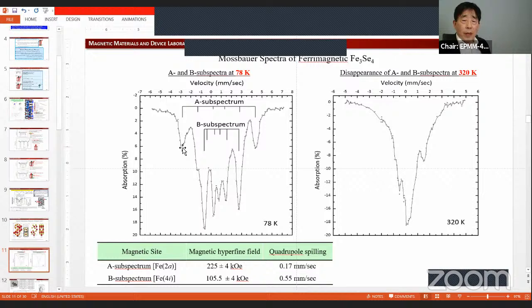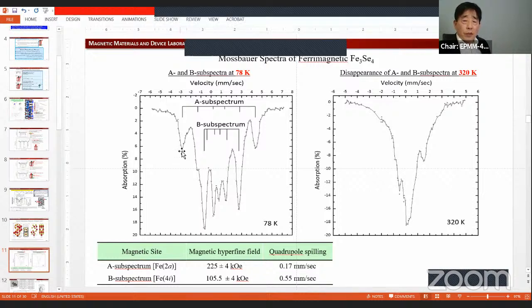The magnetic hyperfine field between this V1 and V6 is much larger than that. And then you can estimate which spectrum comes from which magnetic site, because the iron selenide has two different magnetic sites. A is the 2A site, B is coming from the 4i site. And this is the 2A site magnetic hyperfine field like that, and the B site magnetic hyperfine field like that.